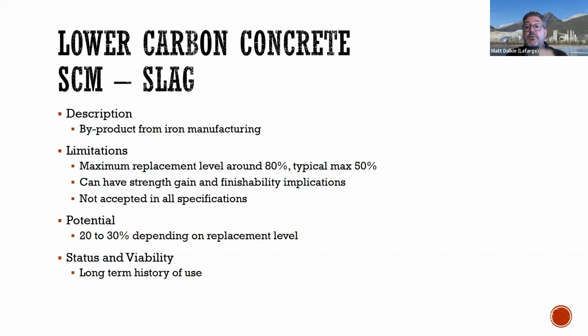But because we can use more of this material in comparison to fly ash, the potential CO2 reductions are higher, again, depending on your replacement level, but between 20 and 30% CO2 reduction. It does have a long-term history of use, and at the moment, it doesn't look like there's the same constraints as far as the availability goes moving forward.